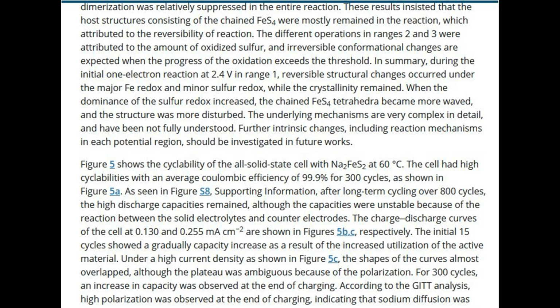The charge-discharge curves of the cell at 0.130 and 0.255 mA/cm2 are shown in Figures 5b, c, respectively. The initial 15 cycles showed a gradual capacity increase as a result of the increased utilization of the active material. Under a high current density as shown in Figure 5c, the shapes of the curves almost overlapped, although the plateau was ambiguous because of the polarization. For 300 cycles, an increase in capacity was observed at the end of charging.